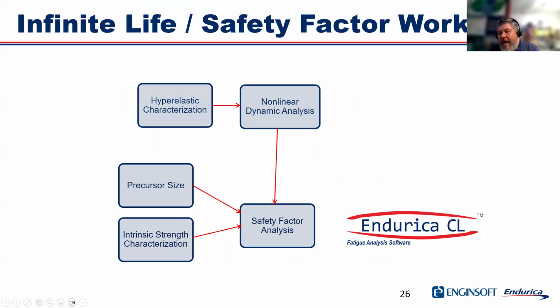Okay, so last topic, let's talk about using the fatigue threshold T naught in a simulation. So this is the workflow where we're going to calculate a safety factor, right? The safety factor is the ratio between your fatigue limit and your worst case load. And so typically this might look like this. Obviously you're going to measure your rubber stress strain response. You're going to do some kind of nonlinear analysis of your duty cycle. You're going to have experimental measurements of your precursor size, and experimental measurement of your T naught value, using maybe the ISA. And those are all going to go into your analysis.